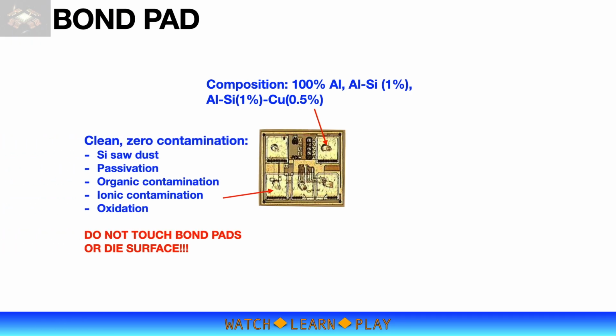Bond pads must also be clean. Must have zero contamination on the surface for bonding to be successful with good integrity. Things to watch out for are silicon dust from sawing process, and also occasionally some dies may have passivation layer overextending to the bond pad surface. Other contaminations are organic and ionic contamination. These types of contamination are not visible, therefore it is very hard to detect.